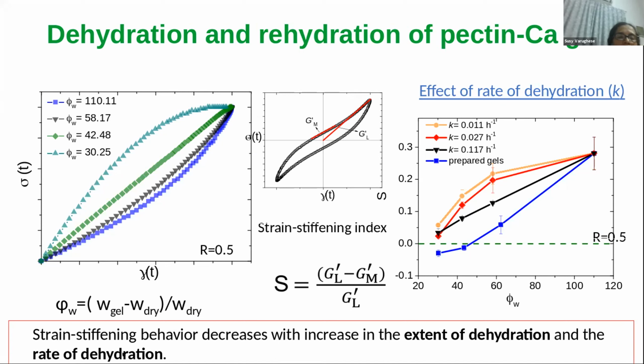So here you can see how much water it has taken up, and when you're drying, you have a wet-dry mass here, and then as a function of that, how the material is showing the strain stiffening or not. So you can see the strain stiffening index also changes. The behavior decreases with the extent of dehydration, and if you're rehydrating, it is also affected by the rate of dehydration. So both can significantly affect the plant's mechanical responses.